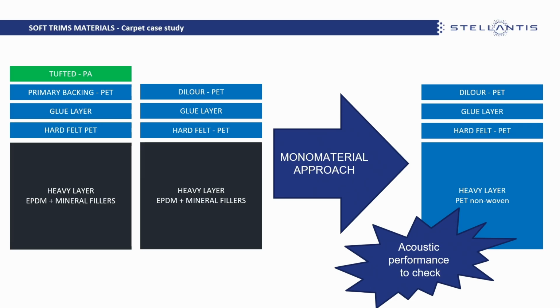Something can be evaluated for the carpets. Also in this case, here we have not so much. We also have PA, but the main material, together with the polyester, is what I call here the heavy layer, that is made of mineral fillers with EPDM. Also in this case, we can move to a polyester non-woven. Here, the main constraint is no longer the aesthetics, so it's not an issue for the designer, but the acoustic performances.